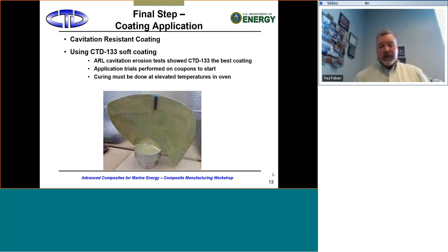One of the leading materials was actually EPDM rubber, but we found when we put it in the water tunnel that we could never achieve a good enough bond of that rubber to the composite that would allow the rubber to stay bonded and take that cavitation. But with the 133 resin coating on there, we found that it was very resistant to cavitation and extended the operation time by years if you extrapolated time. So that's what we went with.